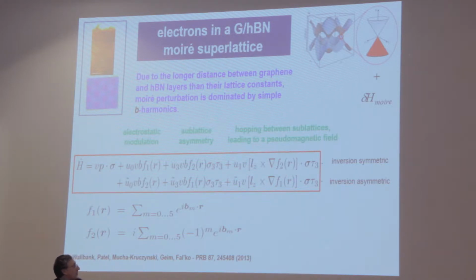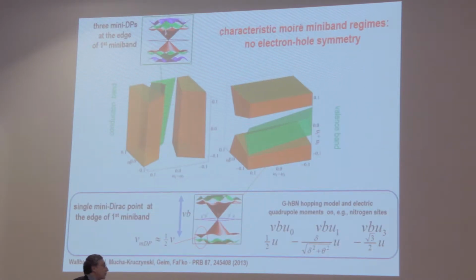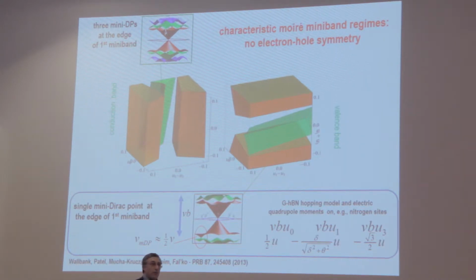In this model that we use, in the long wavelength description of electrons in this Dirac model in the presence of the Moiré potential, we have phenomenological parameters which we initially didn't know at all. So to do this analysis, we just went across a broad range of parameter space to identify what kind of minibands for electrons you're going to get. And then we did two things. We matched that to where in this parameter space simple microscopic models would point to the relevant part of the parameter space.